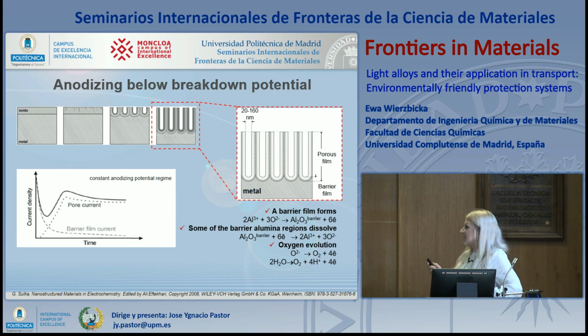Anodizing below breakdown potential is a much better known technique. Firstly, during this process, a thin oxide layer is formed, which corresponds to the current drop. Then, in the place of some imperfection of this layer, a pore starts to form, which corresponds to a slight increase of the current, and then the steady state formation of these long pores occurs, and it corresponds to this part of the current time curve. In this way, we obtain a very long porous structure with a thin barrier layer very well attached to the metal surface.